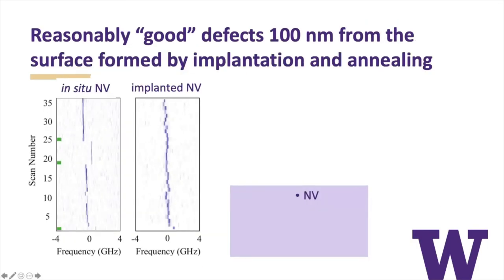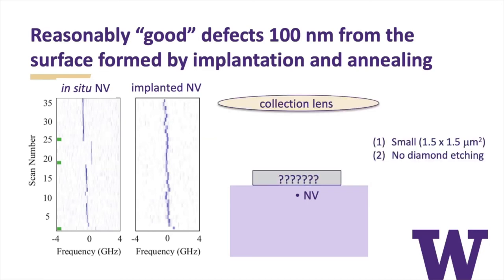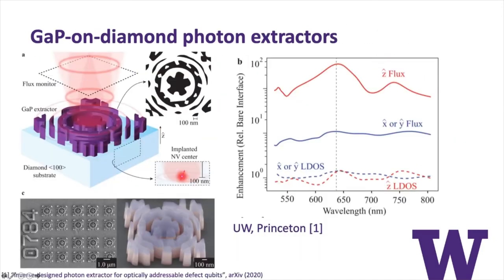We actually got implanted NV centers about 100 nanometers from the surface that were pretty stable. So this is if you're in pristine diamond, where the NV's been grown in, and here's one that's been implanted. And we asked the same question. If we put gallium phosphide on, what can we do? And this is with our collaborators at the Rodriguez group at Princeton. What can we put or do to that gallium phosphide to preferentially have light come into our collection lens? And this is the kind of beautiful structure that they designed and the Rodriguez group made. So this is about 1.5 by 1.5 microns that you see here.